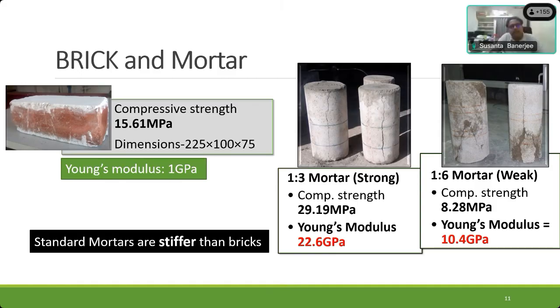So what can be suggested? If we do the testing for one sample, like we do for the shaking table, where the prototype model cannot be cast 3 times, can you do the testing for one sample and get the results? But some material variability is also present in masonry. Correct, and these masonry tests are actually very notorious. Usually the variability tends to be very high, and doing a good test on masonry itself is very difficult. Then doing tests on large scale specimens, particularly the diagonal tension test, is not easy. Getting that experimental test setup working and getting a good result from it takes some time and practice. That is the tricky part of working with masonry.